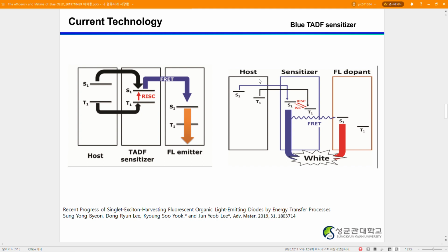One of the most efficient singlet exciton harvesting approaches for fluorescence OLED is to introduce TADF emitters as assist dopants or sensitizers to harvest the singlet exciton of fluorescence emitter by mainly the Förster energy transfer process, which is also called hyperfluorescence. In this approach, the role of TADF assist dopant, which is called sensitizer in this work, is to upconvert triplet excitons into singlet excitons and to transfer the singlet exciton energy to the fluorescence emitter.